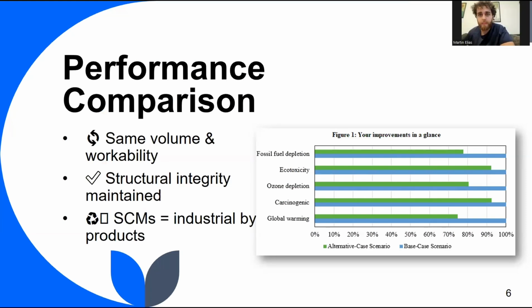So what did we actually improve? The biggest win was a reduction in global warming potential from around 427.5 kilograms of CO2 per cubic meter in the BCS to just 277.4 kilograms in the ACS. That's a 35.1% improvement. On top of that, we maintained similar proportions in volume for a fair comparison and to ensure the structural integrity of the mix was not compromised. Overall, our simplified LCA showed us that even small changes in material composition, like using industrial byproducts, can lead to significant environmental benefits without sacrificing performance.